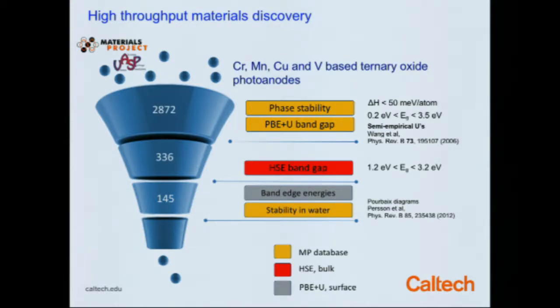In this case, we're interested in transition metal oxides—chromium, manganese, copper, and vanadium-based ternary oxides. We're starting with about 3,000 candidates. These were screened using the band gap calculations at the PBE level and phase stability.